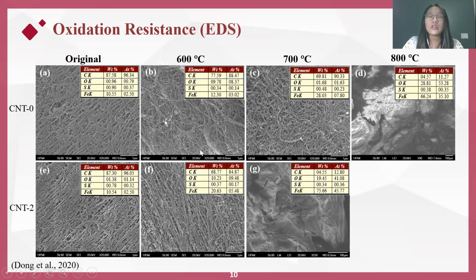At 600, which is about 580 Celsius on the sample, the relative iron content of the CNT2 group has increased to over 20%, suggesting the initiation of carbon oxidation, which corresponds with the first derivative weight peak in the TGA curve. And that of the control group remained relatively constant at around 10%. This discrepancy was further magnified by 700 Celsius, when the CNT2 group had accomplished the oxidation, and the oxidation of CNT0 group was not completed until 800 Celsius. So the earlier oxidation of the water-assisted CNT2 samples could be attributed to their smaller diameters, resulting from the removal of amorphous carbon layer on the catalyst nanoparticles before the CNT start to grow.